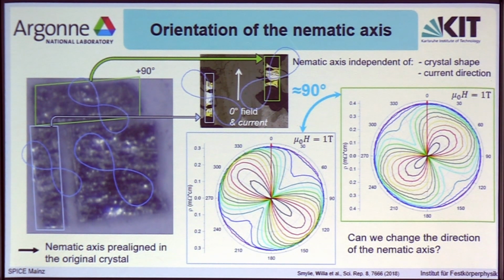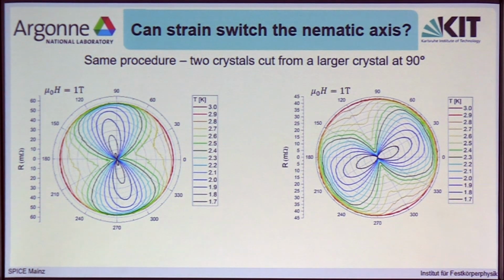Now, since I might be probably the only experimentalist in this room who has never touched one of the strain devices, we've actually at Argonne conducted a very poor man's experiment of trying to change the nematic axis. I'm nevertheless showing it now to you. So we've taken 2 crystals that were cut with the same procedure, 90 degrees away from each other, and mounted them. We've measured those upper and lower critical field maps, or in some sense the high and the low resistance maps. You can see they're related by 90 degrees.